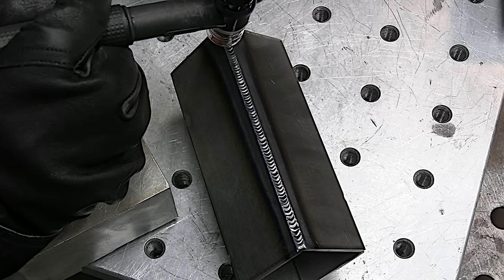Here I want to show you the very end on the way I taper off from an end sometimes. Leave that wire in there to keep from blowing it away and then back up as I let off current. Taper it down into like a teardrop shape.